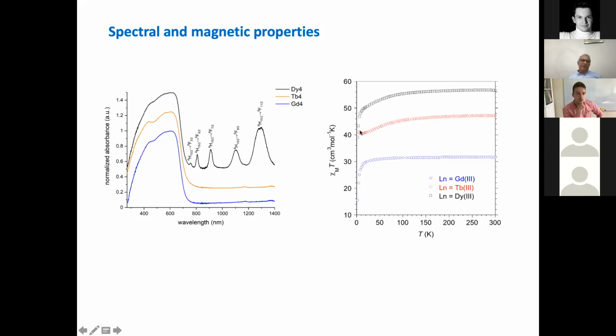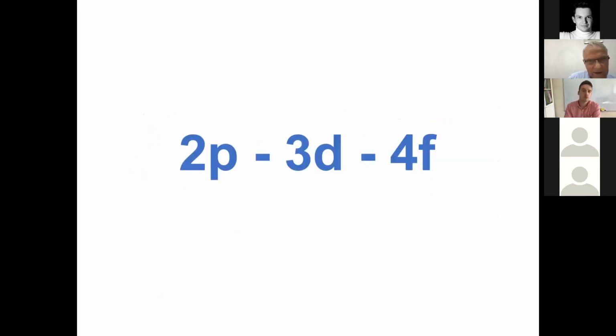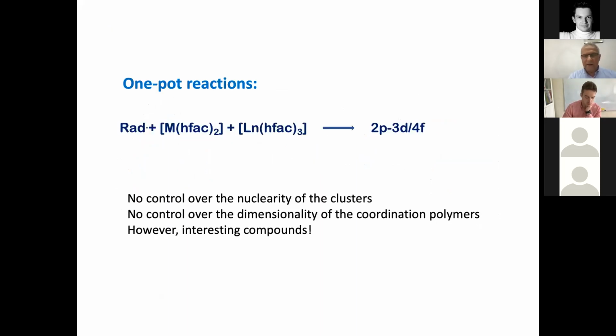So the treatment of the data together with the ab initio calculations are in progress, so I will not insist much on these compounds, just mentioning that unfortunately for the terbium and dysprosium derivatives, we do not observe the slow relaxation of the magnetization. So the final aim of our work is to design systems containing 2p, 3d, and 4f